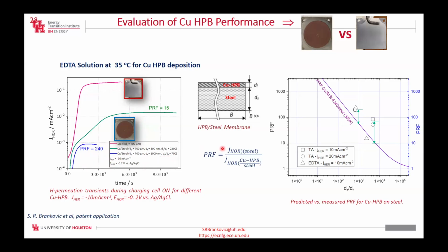steel wall. And therefore, when we look at the calculations that we could do from the literature data, we can see that our permeation reduction factors are almost an order of magnitude higher for the given ratio in the thickness between the steel and the copper permeation barrier. So we are doing pretty good in terms of deciding what material to use and how to form these barriers.